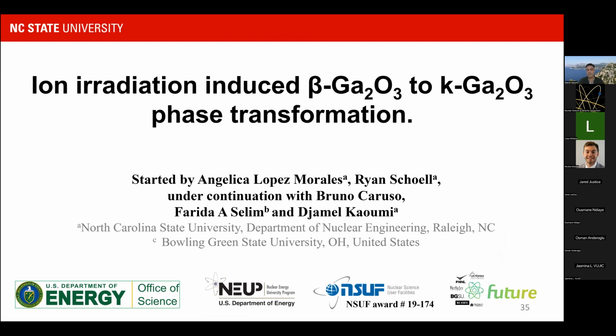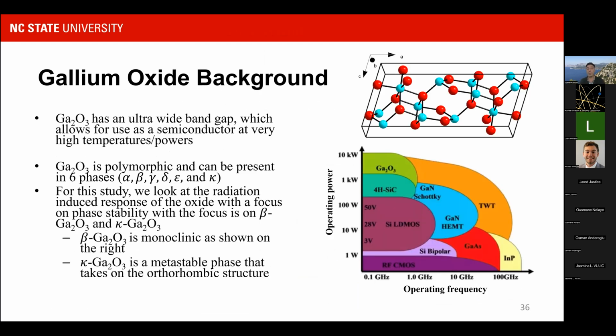All right, I would like to finish with an example that is relevant to this consortium. In fact, it's a study that I started with my previous student, who graduated now, but is now under continuation with Bruno, who's actually part of this consortium, where we look at the effect of irradiation in gallium oxide. The reason why we're looking at gallium oxide is essentially for its properties and its potential for use as a detection material. Gallium oxide has an ultra wide band gap, and that's actually what makes it attractive as a semiconductor that could work at very high temperatures and very high powers, so in harsh environments. But there's not a lot of information on how it would behave under irradiation.